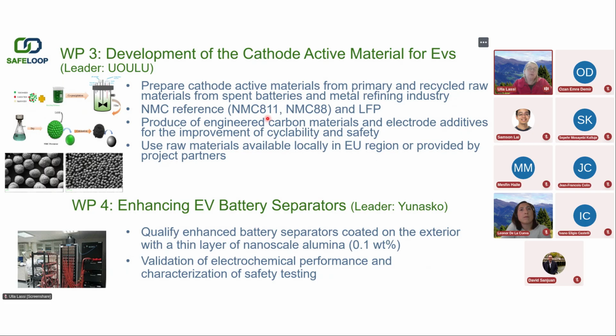Then our Ukrainian partner, Yunasko, will work with the battery separators. They are developing battery separators which are coated with a thin layer of nanoscale alumina, with a very small content of the nanoscale alumina, to improve battery safety, especially when we use high C rates for battery testing.